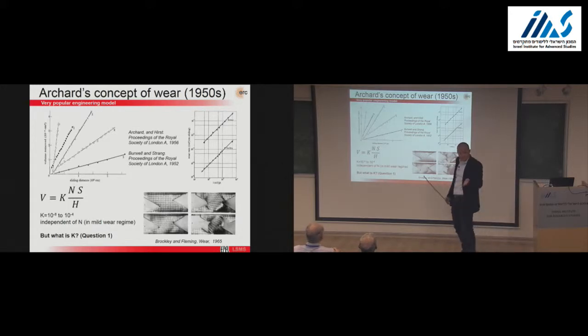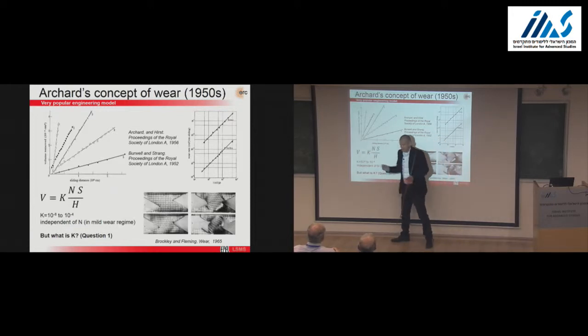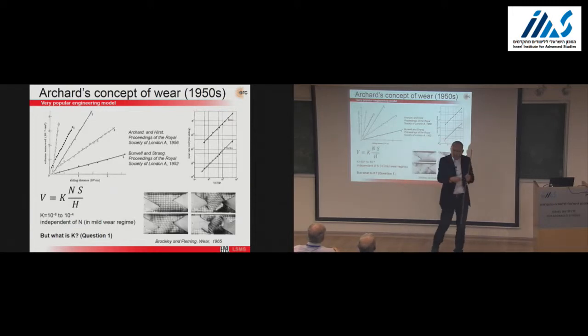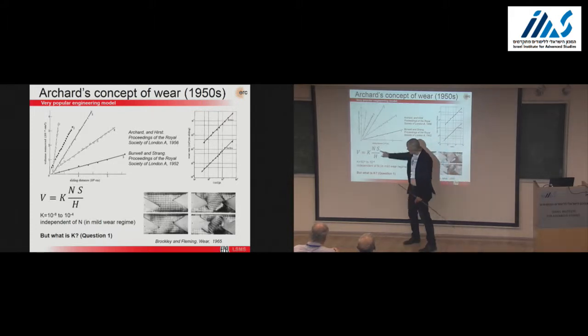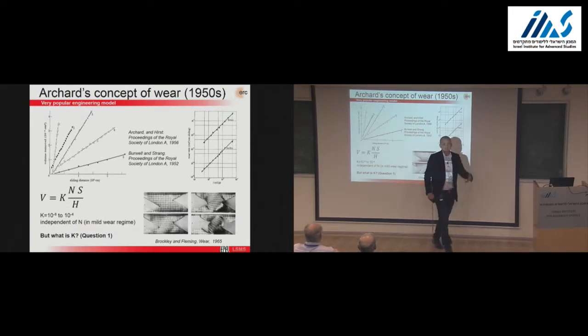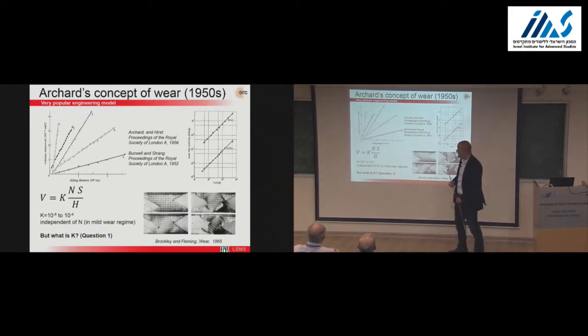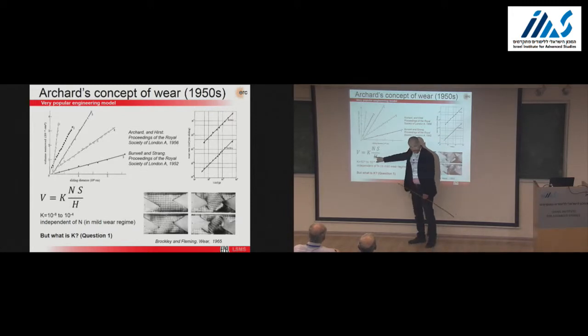It's a model from the 50s, and it's very used in engineering because it's used to predict the lifetime of a mechanical component. So it tells you that the wear volume, and you measure this by collecting the pieces of debris that fall out of a contact, well, the wear volume is going to be proportional to the normal load, and there's data showing this. So it's linearly proportional, at least within a range of normal loads. It's linearly proportional to the sliding distance, so a usage life, and inversely proportional to the hardness. Okay?